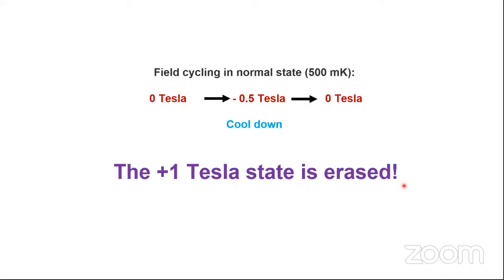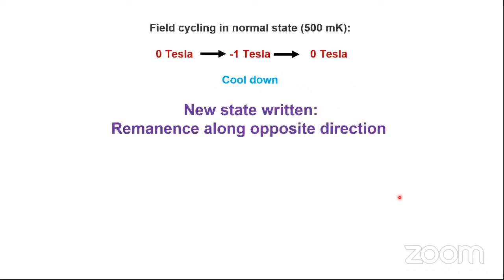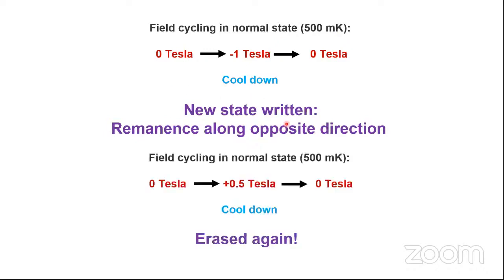I'm not showing too many RT data because that will clutter the slides, and you know what it will look like if I actually show the data. And then we did the field cycling at 500 millikelvin to minus 1 Tesla, and cooled down. We found the remanence pointing upward and erased that by applying a field of 0.5 Tesla upward. And in all these cases, we are going to the normal state to write the magnetic state, and coming back to the superconducting state to use the superconductor as a sensor.